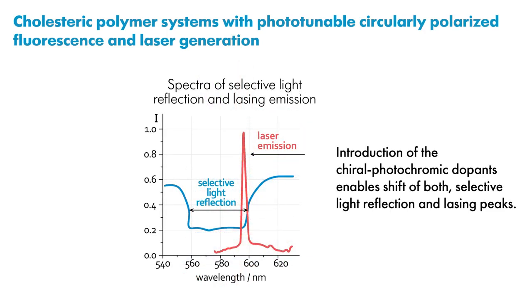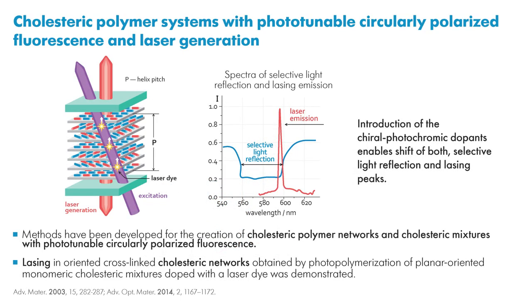Usually, laser emission is observed at the long wavelength edge of the selective light reflection peak. Introduction of the chiral photochromic dopants enables shift of both selective light reflection and lasing peaks. Lasing in oriented cross-linked cholesteric networks, obtained by photopolymerization of planar-oriented monomeric cholesteric mixtures doped with the laser dyes, was demonstrated.